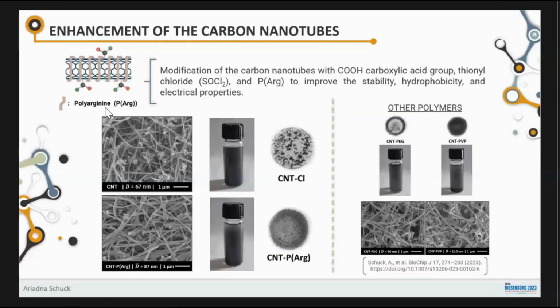So first, the enhancement of the carbon nanotubes. As I mentioned before, I already published this work in the Biochip journal, if you want to check the references here. And then I compare the enhancement of the carbon nanotubes doped with thionyl chloride to increase the conductivity of the carbon nanotubes, also the active layer, because even though I have a working electrode made of gold, when I coat that with carbon nanotubes, the conductivity will decrease anyway, because carbon nanotubes are not as conductive as gold. But I can improve this decrease of property by enhancing with the doping of thionyl chloride.